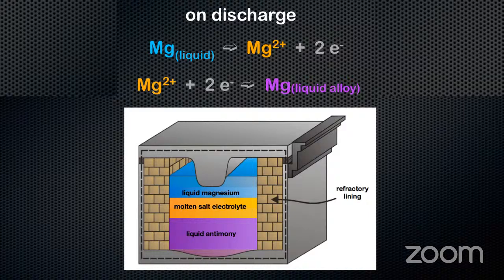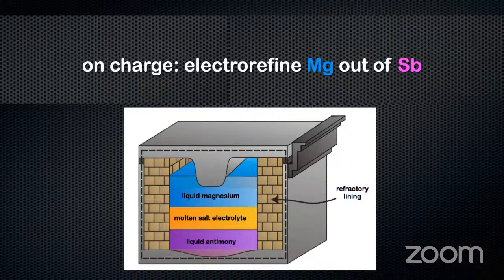So now when I want to discharge, I connect the magnesium and the antimony to a load, and the magnesium wants to get to the antimony, but I just told you magnesium is insoluble in the molten salt. But magnesium is smart. Magnesium knows if it loses two electrons and becomes magnesium ion, the magnesium ion can go into the salt. And those two electrons come off up here and go through the external circuit. And then when magnesium gets to the bottom, it picks up the two electrons and alloys with the antimony. So over time, the top layer gets thinner, the bottom layer gets deeper. And then when we go to charge the battery, we force current through and we electro-refine. We send the magnesium back to the top.